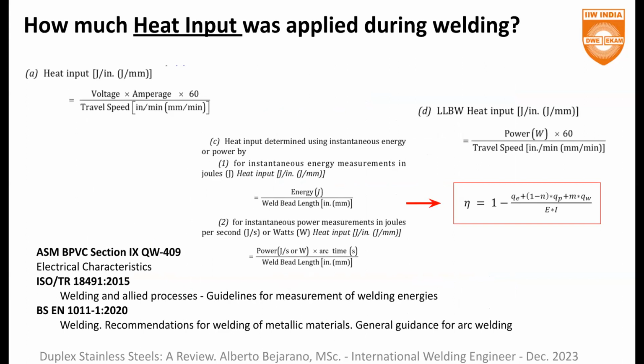This is quite interesting. How much heat input was applied during the welding? Probably the most tricky thing when you are welding duplex stainless steel is that the cooling rate must be adequate. And when I say adequate, it means that it can't be very low or very high.